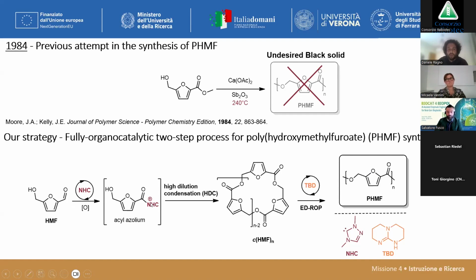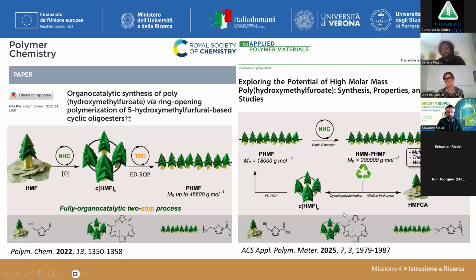We were able, working with N-heterocyclic carbene under high dilution conditions, to synthesize a mixture of macrocyclic oligoesters, and then to open them in an entropy-driven ring opening process, organocatalyzed by TBD, to obtain for the first time polyhydroxymethylfuroate.